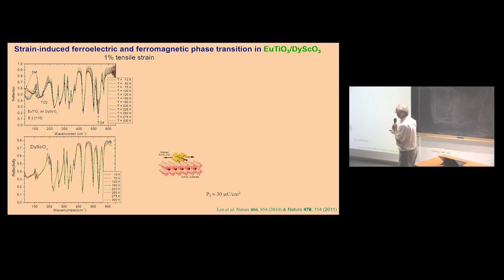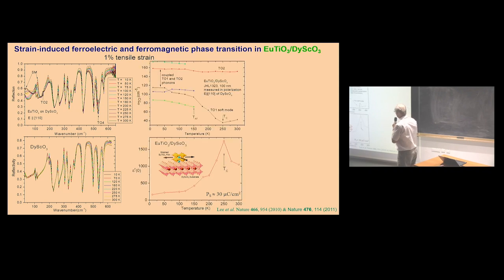If you have a thin film, in this case 100 nanometer thick, we have difference here, and this is reflectivity from the soft phonon, and on cooling we can see finally hardening of the phonon from here to here. So finally what we observe, that soft phonon is at room temperature very low, it softens and then again hardens. So here is a signature of ferroelectric phase transition.